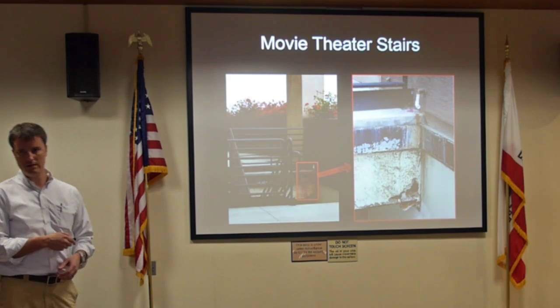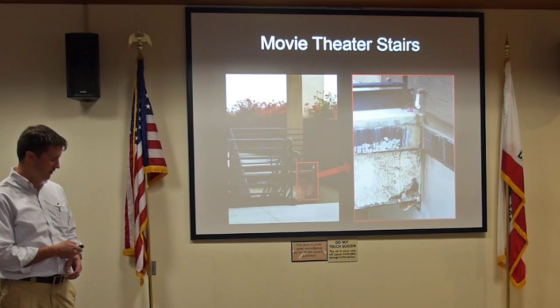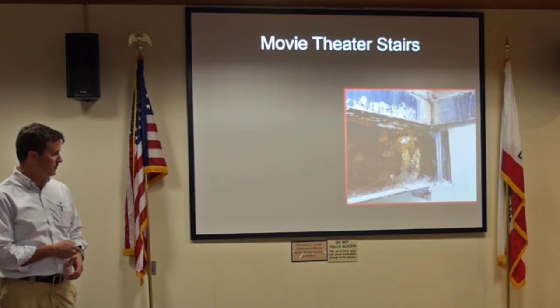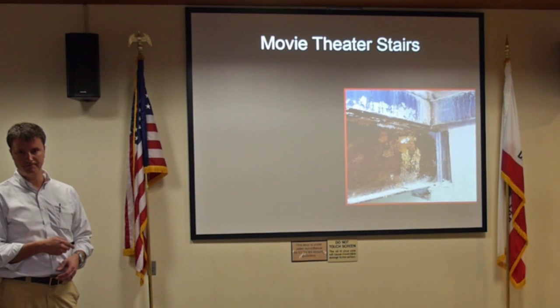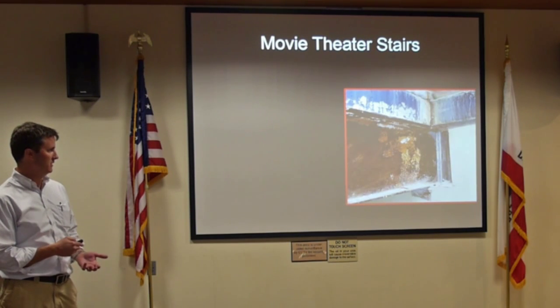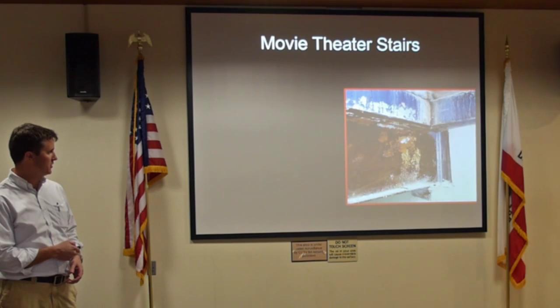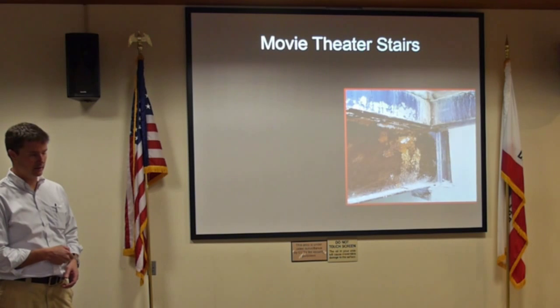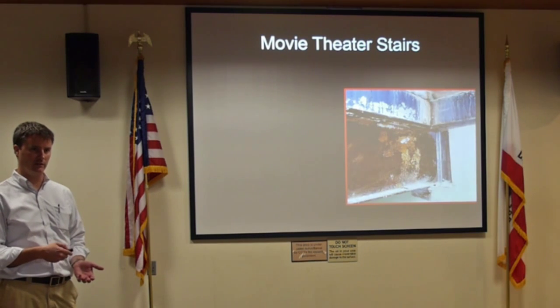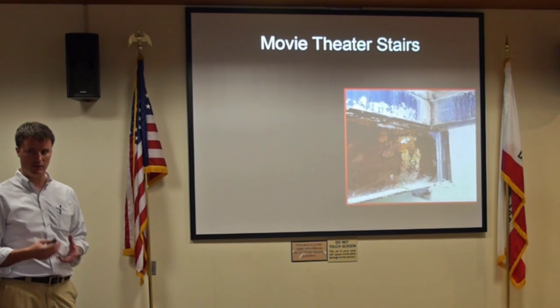That's the area where we have the initial concern. Once we remove the fireproofing, you actually see it's fairly corroded. And the other thing that is of large concern is that it's a little tough to see in this photo, but this is actually coming down at the end of the beam where you have bolts of connection. These bolts are what's called slip critical, so any amount of section loss is very concerning.